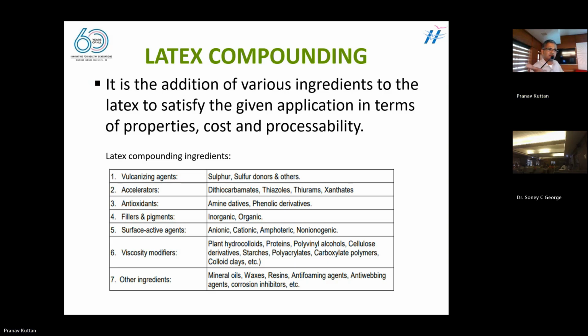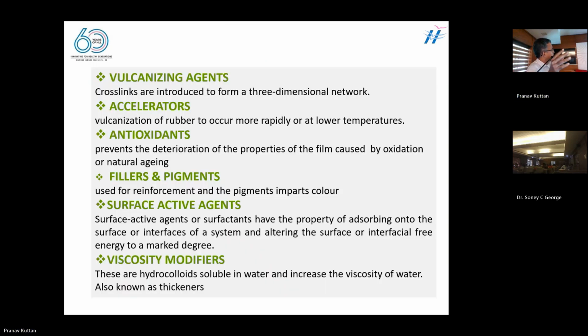So we are using different pigments for the products, fillers. Then we are using some surface active agents to keep the colloids in a stable state. We are using viscosity modifiers in the latex for keeping the viscosity at the correct level so that the product can be formed. And then we use other ingredients like waxes, oils, anti-foaming agents which resist foams, anti-webbing agents to prevent webbing, and all such constituents. So these are the materials you are adding: vulcanizing agents, which introduce the three-dimensional network; accelerators, which speed up the reaction; and antioxidants, which prevent oxidation. Fillers give colors. Surface active agents will help the system work much better in the later stage. And viscosity modifiers keep the viscosity at a level which is good for the product to be formed.